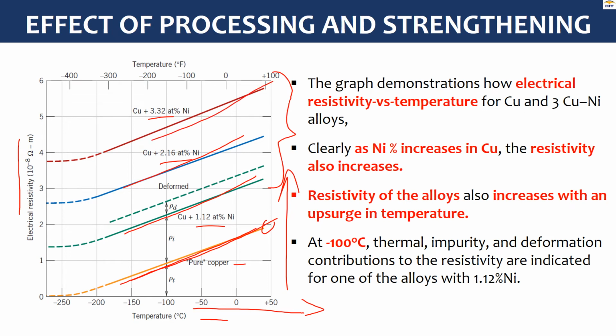these lines here. Okay, if you take maybe for example at minus 100 degrees, we can see here the thermal, impurity and deformation contributions to the resistivity. Here we can see this is for your pure copper. This is copper at 1.12 here, and now this is the one that is deformed. Okay, so electrical resistivity actually increases with deformation here. Okay, so you've got your resistivity for your thermal ending here. Then you've got your resistivity for your impurity, maybe ending somewhere here. Then resistivity when you now include also some deformation ending somewhere here. Okay,